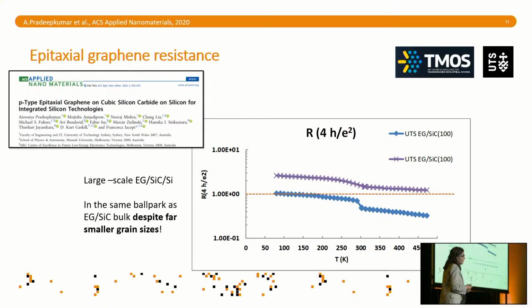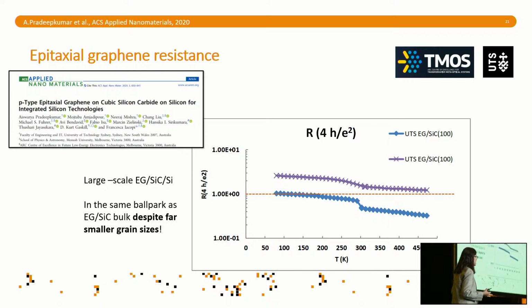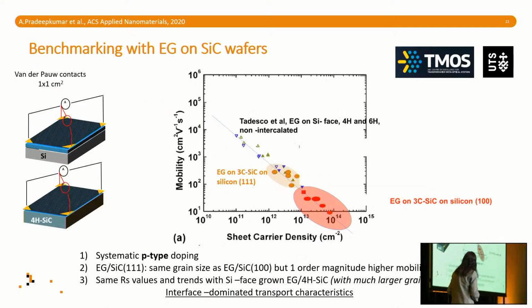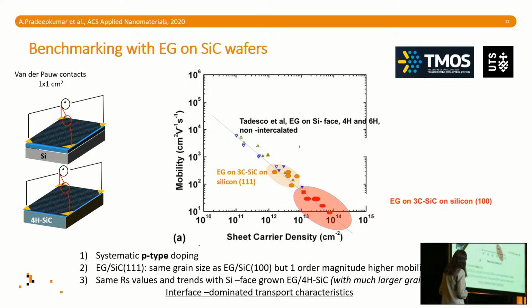Before I get to that, though, I needed to make a point about the conductivity, because clearly this is one of the properties that one wants to use about graphene, the really high conductivity. And it turns out, actually the next slide explains that even better, that our conductivity is pretty much in the same ballpark as the epitaxial graphene on silicon carbide ingots, wafers, the ones that actually have microns-large grain sizes.